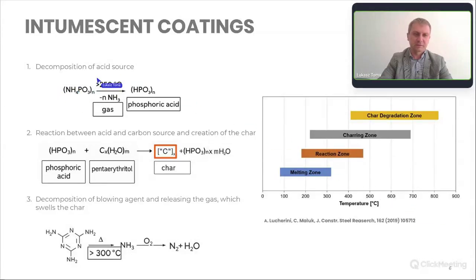We have an acidic source, which is predominantly ammonium polyphosphate. We have a source of carbon, which is necessary to create the char, and a blowing agent, which expands the char. So what happens during the fire? Above 250 degrees Celsius, we have the decomposition of the acid source to ammonia and phosphoric acid. Then the phosphoric acid reacts with pentaerythritol and creates the char. And above 300 degrees Celsius, melamine decomposes and creates different kinds of gases which expand the freshly formed char.